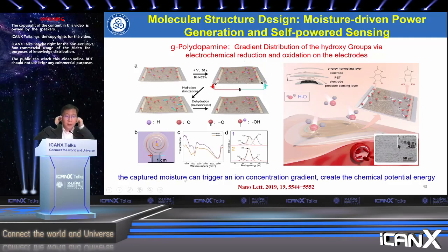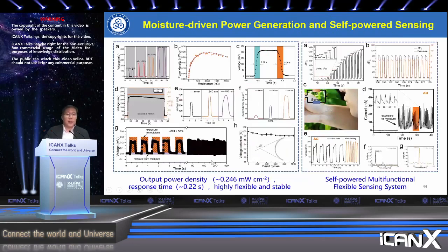So we utilize the chemical potential energy, which widely exists in spontaneous diffusion processes such as moisture diffusion, which can trigger an ion concentration gradient and create the chemical potential energy. And it can work as an energy harvesting layer to provide the power for, for example, the flexible pressure sensing layers to get the self-powered sensing systems. And it has a very good output power density, about 0.246 milliwatt per square centimeter, and a fast response time, and is also very flexible and stable.